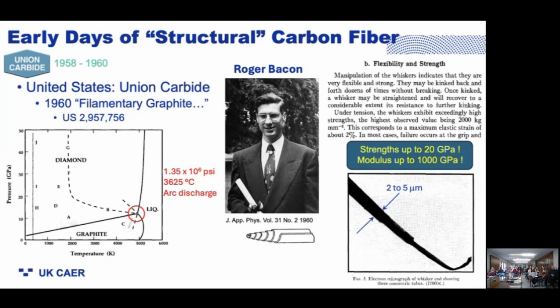Just to be clear, that's more than double the tensile strength of the best carbon fiber you can commercially lay your hands on these days—also with a modulus of about 1 terapascal, or 1,000 gigapascals. This is consistent with loading graphite along the basal planes, like a perfect single crystal graphite. So these were essentially little perfect, almost perfect, single crystal whiskers of graphite.